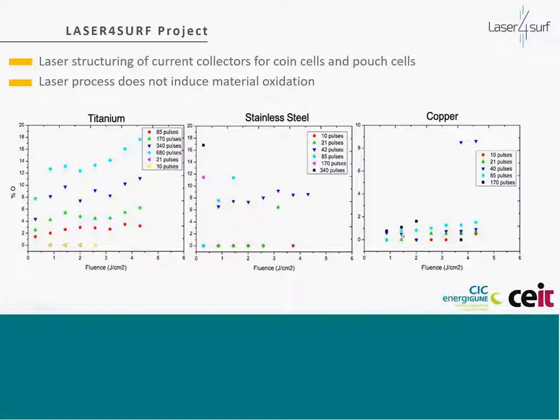Take into account that these are the values that we get for copper, but if you compare them to the ones we get for stainless steel or titanium, these are much lower for most of the process conditions. So it is a good point that we can control the geometry of the structures we produce on the surface, and that we can also do it without a significant amount of oxygen content for the subsequent processes.